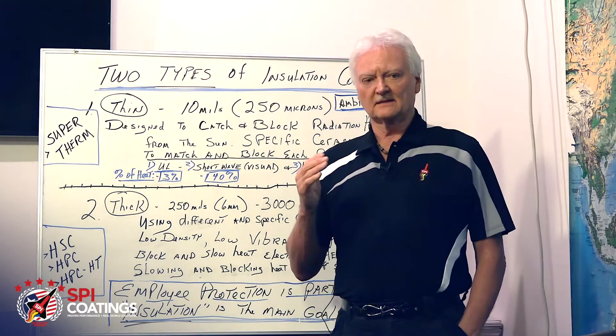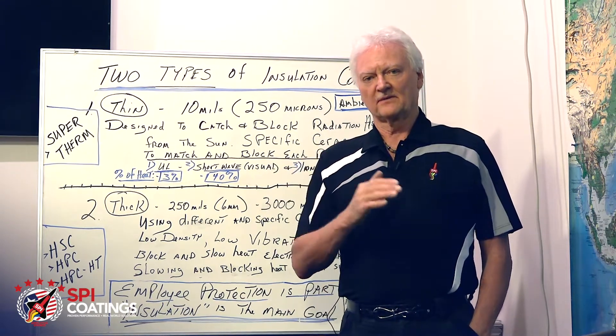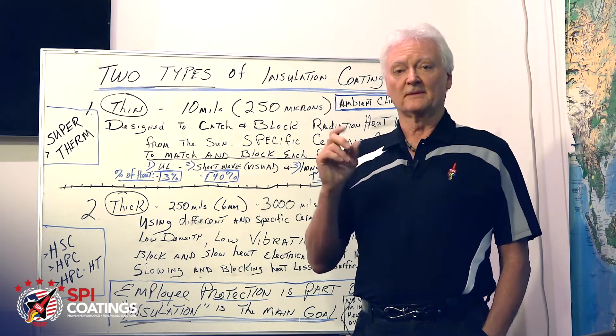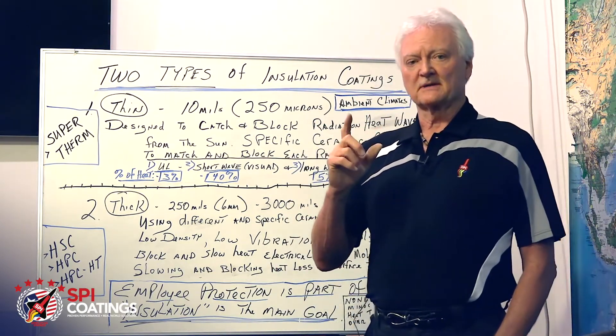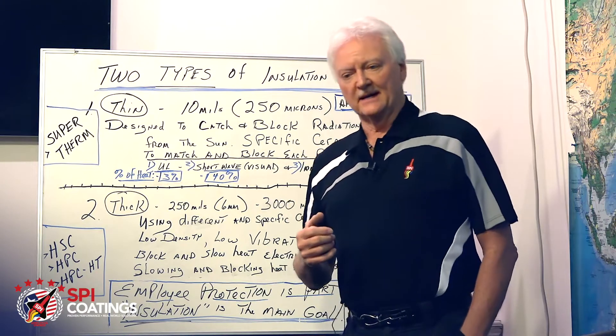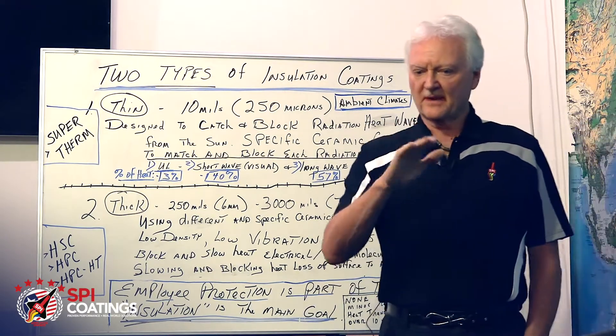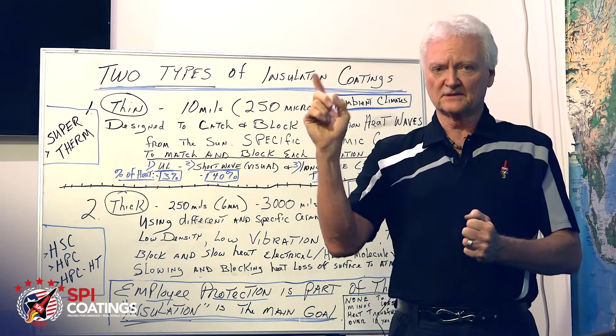In the field of insulation, there's thin film and thick film, and one coating is not going to do it all — unless you have a very thick coating, like a quarter inch, and you're hoping the thickness does the trick. But the more thick you are, the more shrinkage you might get over time and have some adhesion problems over seams. In the design of something, what you're looking for is the ceramics doing the job. The resin is just there to lay it out, pull them together, hold them together and lock it down so the ceramics can do the job, not the thickness.